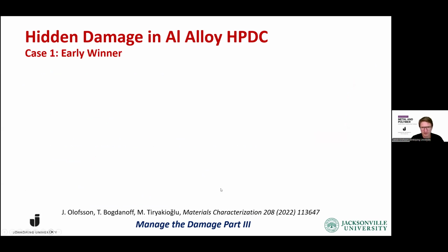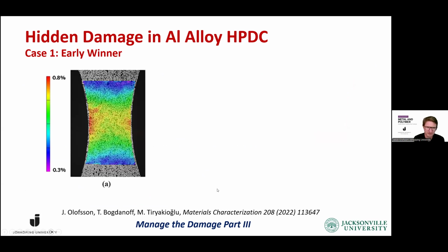And the results here we can look at in different cases. So the first case here is what we call an early winner. If you look at the strain field here, at a low load level, it kind of resembles what we saw in the FEM simulation, that we have a higher strain near the thinnest area here, but also a bit up there to the left, you can see that there's already something happening, which is not really following the symmetrical strain distribution that we would assume here.